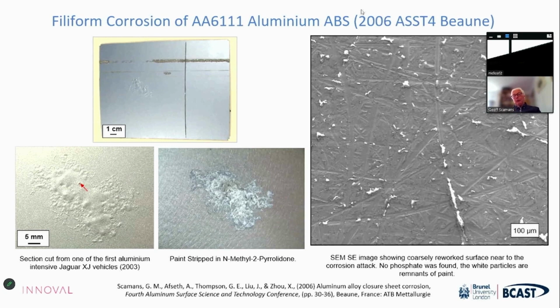When you look at the SEM image on the right, you can see all the marks from the grinding that had been done before painting. And the obvious remedy for this was to stop doing the grinding before painting. And once that stopped, we don't see filiform anymore under painted outer panel products on aluminium cars. So it was a worrying time, but simply resolved again by careful work done at Manchester. And we reported that at ASST4 in the wonderful French city of Beaune, where they provide nice alcoholic refreshment.